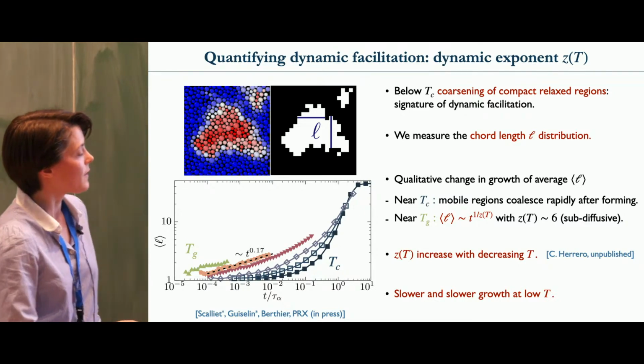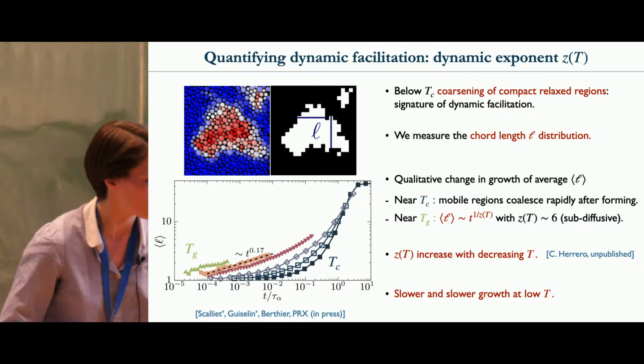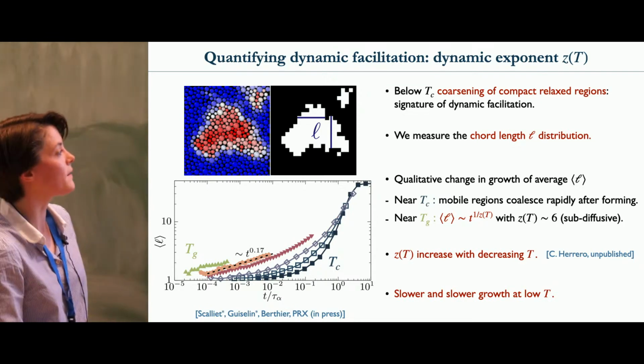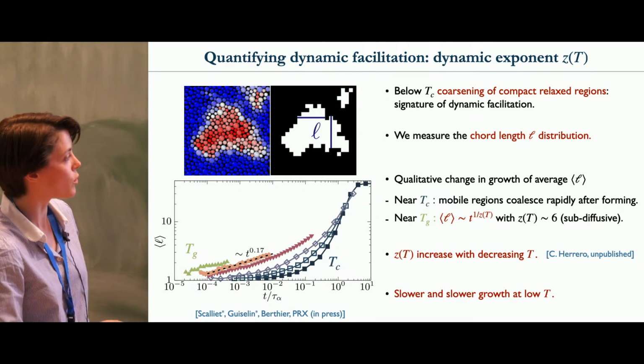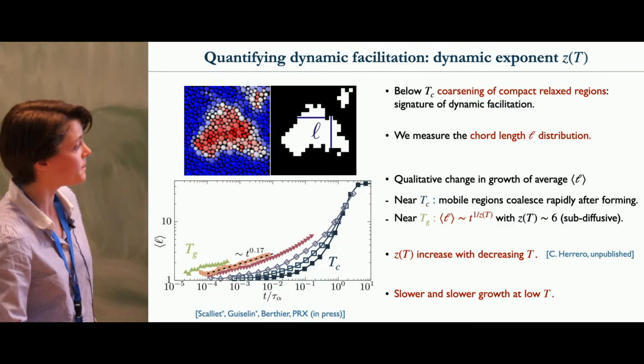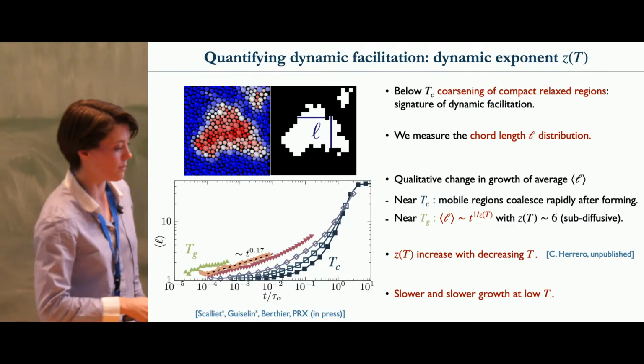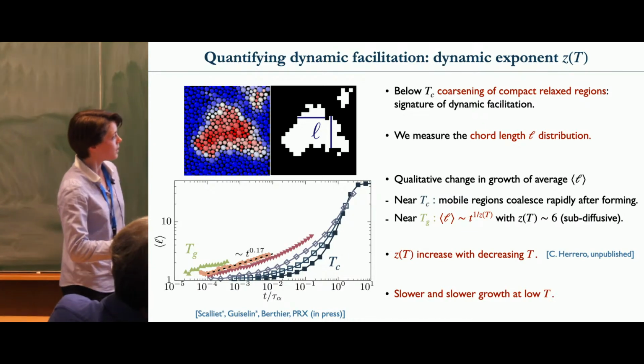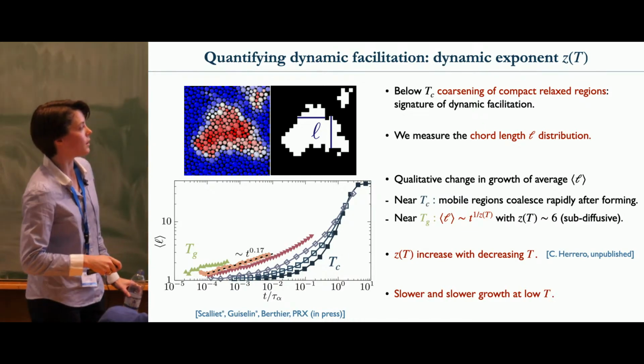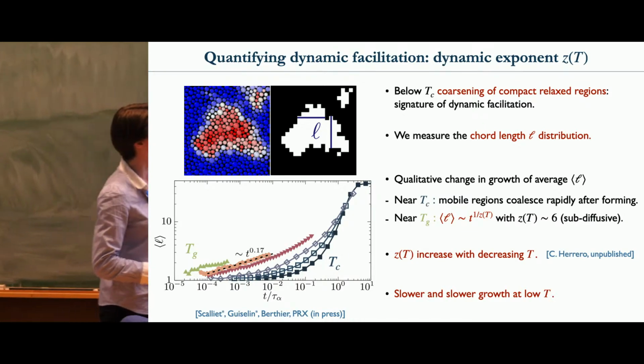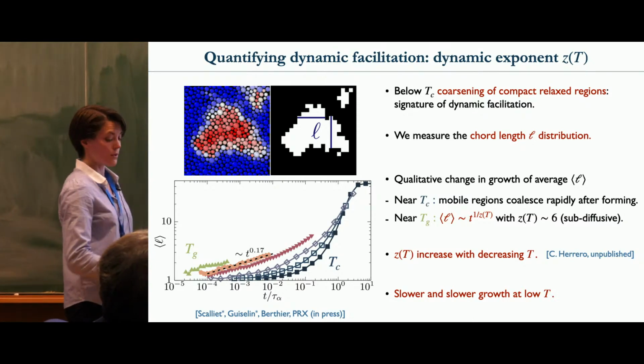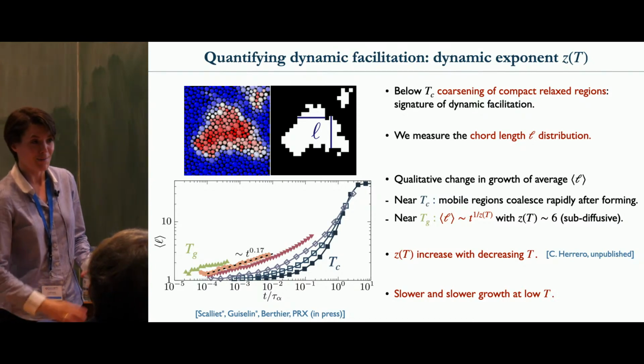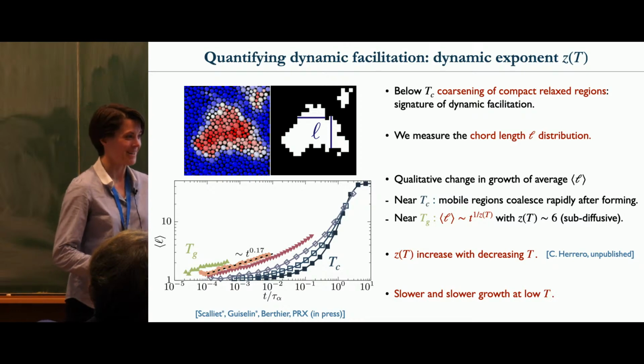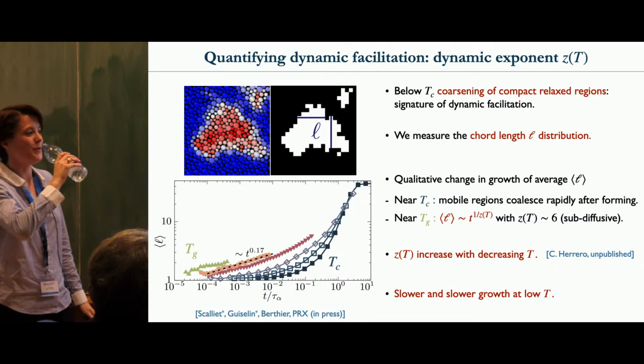So here I'm showing the data as a function of different temperatures, from high temperature, corresponding to the mode coupling crossover, to much lower temperatures corresponding to TG. And again, this is rescaled by the alpha relaxation time so that we can compare different temperatures.